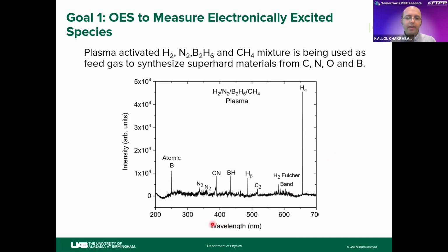So diborane, hydrogen, nitrogen, and methane were present in the plasma. As you can see, we can get atomic boron, BH, nitrogen, CN, C2, and hydrogen peaks in the optical emission spectroscopy. Our next goal was to see if we can tune or modulate those atomic boron, C2, or CN peaks in the plasma so that we can synthesize our desired phases in our microwave plasma CVD chamber.